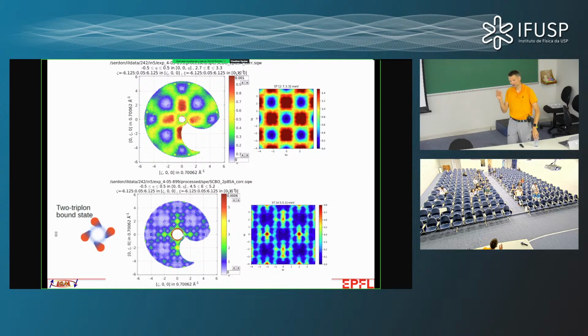Okay. No. I went really fast here towards the end, I apologize for that. There are two different experiments. This experiment is a zero pressure experiment, performed on a type of neutron spectrometer called a time of flight spectrometer, which allows us to measure very large regions in reciprocal space as a function of momentum. These are two directions in momentum space. That's how we can measure the intensity or the structure factor of these excitations over a wide range. This is done at zero pressure, so the sample is just sitting there in helium exchange gas. We can have big crystals, so we have a good signal, low background. Okay? So that is what this is.